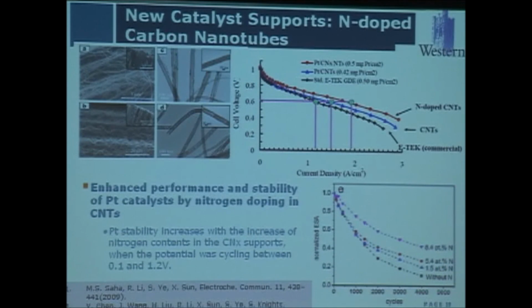In this example, compared with a conventional catalyst and a regular functionalized carbon nanotube, we get some improvement in the high current density, but no improvement at all in low current density. The high current density improvement is mostly because of the structural benefit of the carbon nanotube. However, if we use a nitrogen-doped carbon nanotube, we improve both low and high current density. So that means we not only take advantage of the carbon nanotube as a structure builder, as I call it, but also improve the platinum dispersion.